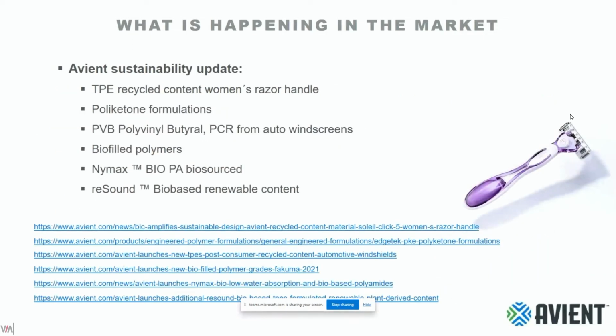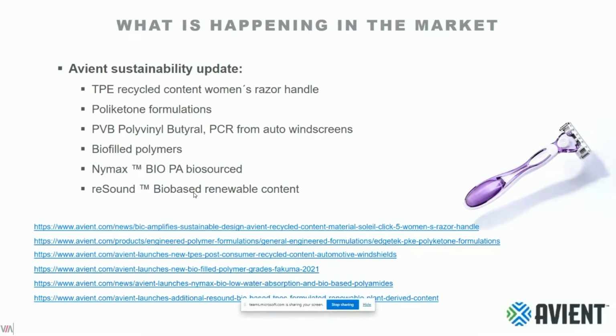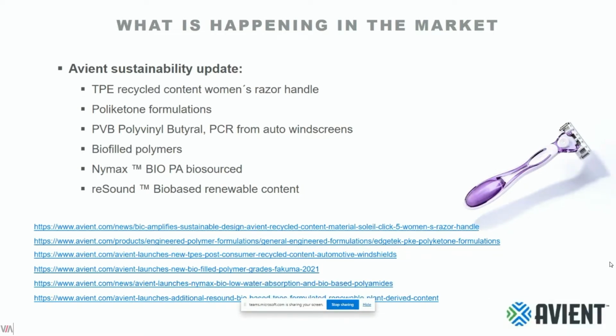We have more solutions related to sustainability in Avient. You can see we reduce the CO2 footprint in the material production and also during the material transformation, due to the lower transformation temperatures compared to polyamide solutions. We have the new TPEs with PVB, polyvinyl butyral content, coming from auto windscreens. We'll see that at the end. We also have biobased polymers, both in the resin base and in the fillers. The new NYMAX grades are polyamides based on biosourced materials, and also reSound grades with bio-based renewable content. You see below the links, where you can dig deeper into further details.